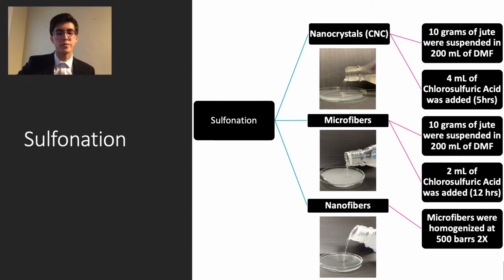Following the pretreatment process, the sulfonation reactions were attempted. Basically, 2 parallel reactions were run. One reaction was run to synthesize nanocrystals, and the other was run to synthesize microfibers. The nanocrystal reaction involves suspending 10 grams of jute, which was bleached and mechanically ground, into 200 milliliters of dimethylformamide, which is an organic solvent. Following this, 4 milliliters of chlorosulfuric acid was added, and the reaction was allowed to run for 5 hours.